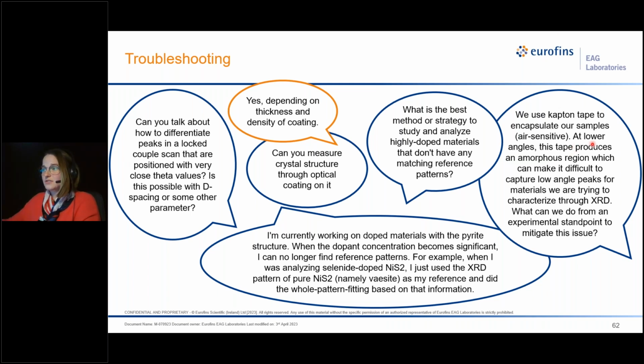If you use Kapton tape, again, it's going to produce an amorphous peak at the lower 2 theta range, but it's not going to cover small intensity peaks, because when you have multiple things, the X-rays are additive. So if you have a large amorphous peak and a very small intense peak, that small peak will sit on top of the amorphous peak because they add. The only issue where you might not see this is if you have a poor signal to noise, where you might miss that small peak. So longer collection times, or collecting your sample holder with the Kapton tape without the sample in it so you can do a subtraction, might help you see that smaller peak as well.